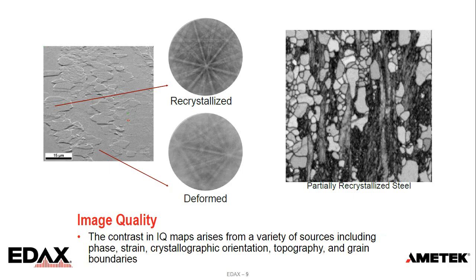And we can see an example of this from a different steel. This is a partially recrystallized steel. IQ map contrast can come from phase contrast. That will just be difference in scattering from atomic number. It can come from, the generic term is strain, but as we deform the lattice, the diffraction is not as sharp, so the peaks are not as bright. Crystallographic orientation, some orientations will have more lines or more poles in it, so we'll end up brighter in the Hough transform. Topography and grain boundaries.